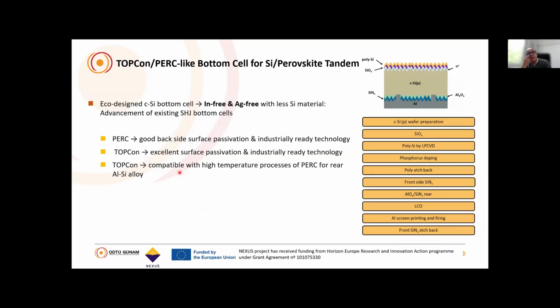Another topic we are focusing on is the bottom cell, which is very attractive and promising as far as we see. In this case, the cell structure is shown up here. The backside is very much like a PERC cell, but the front side is different. On the front side, we have a polysilicon layer and the TOPCon structure. On top of this TOPCon structure, we use aluminum-doped zinc oxide for the recombination junction for the perovskite top solar cell.